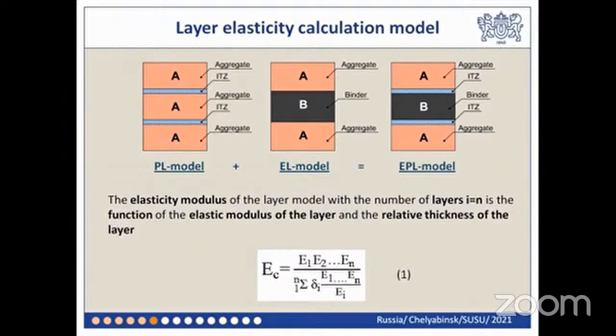Developing a calculation model of the composite deformative properties, a dependence of the elastic modulus on the layer model was proposed, with the number of layers n, the elastic modulus of each layer, and the related thickness of the layer. Further, the testing of layer model applications is presented.